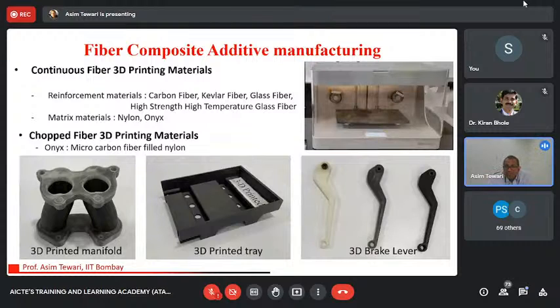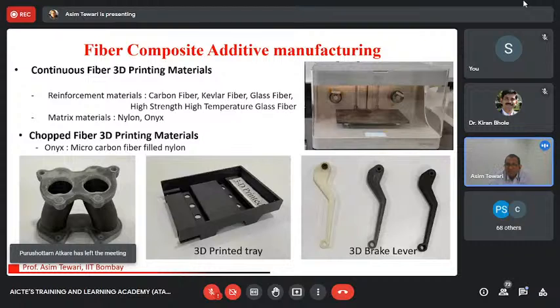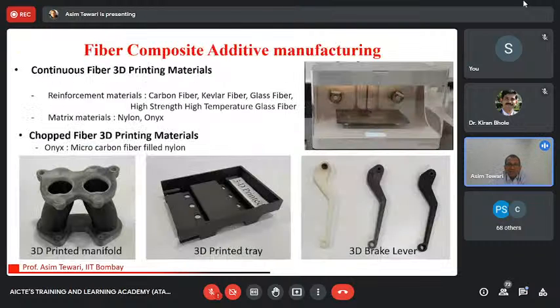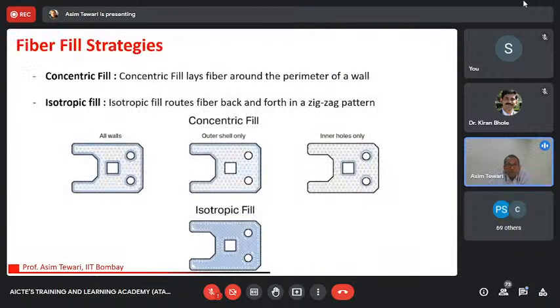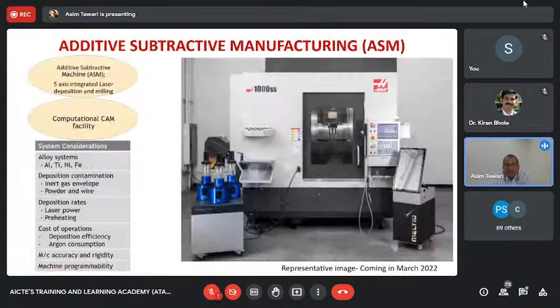So these 3 are the exact same geometries, with the carbon fraction varying from 0 to the maximum, which is about 35%, 40%, which we can achieve in this case. And this has been created using additive manufacturing. So we can actually print carbon fibers, Kevlar fibers, glass fibers, even high strength high temperature glass fibers. So there are many different fibers which we can add and print. And of course, there could be many other complexities which you can build around it.